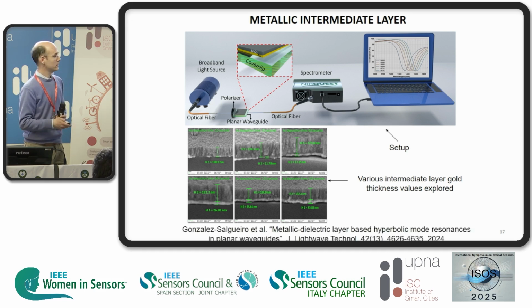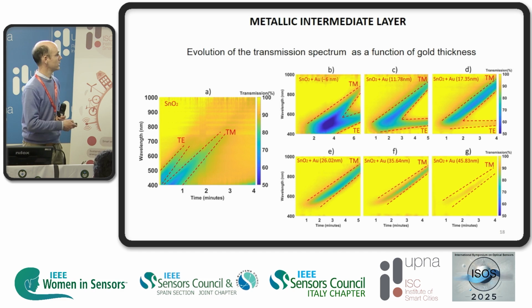And we compare the results by using all these structures. So the evolution of the transmission spectrum as a function of gold thickness is shown here. Here there is no gold, and we observe the TE band and the TM band, and as a function of wavelength it fades. This is a typical problem, especially in planar waveguides: at longer wavelengths quite often the resonance is lost. However, with the gold layer, the position of the bands is exchanged. This is quite surprising. We have analyzed it with modal analysis, but I won't focus on that now.